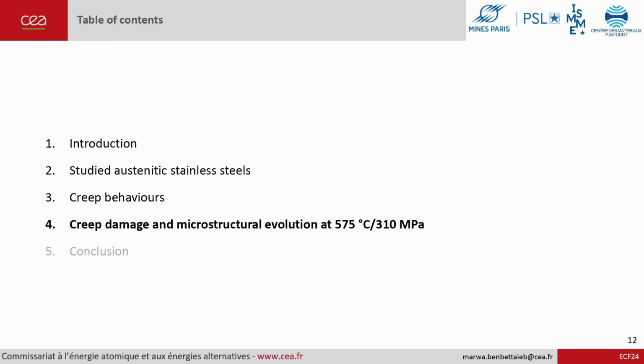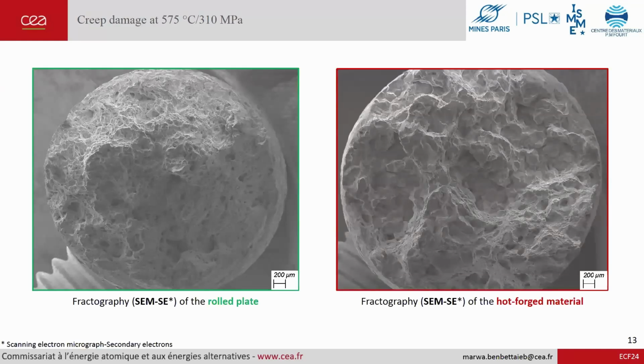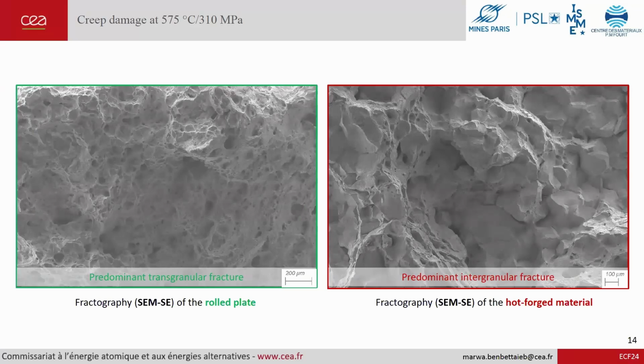If we take a look at the creep damages, here are two fractographies. On the left, the fractography of the niobium-free alloy, and on the right, the fractography of the niobium-rich alloy. So visibly, we have different fracture types. If we look at zoomed in images, we can note through those dimples that the fracture is principally transgranular for the niobium-free alloy, and according to this image, where we can note the presence of straight edges and shiny surfaces, that the fracture is principally intergranular for the hot forged material.